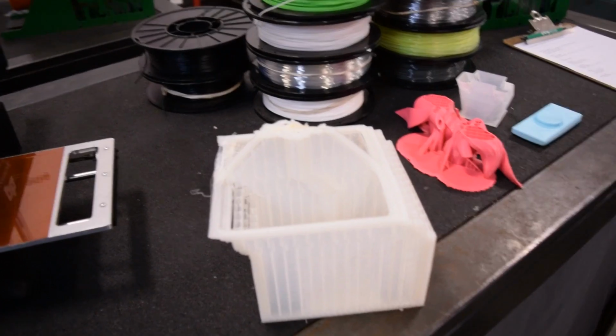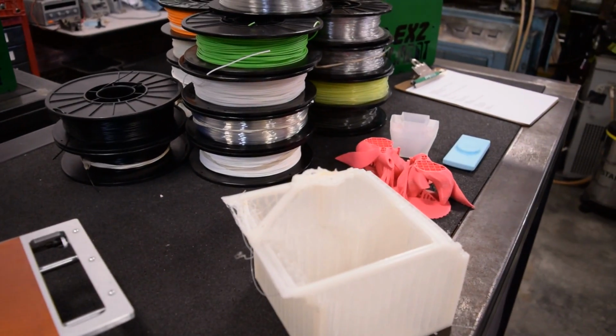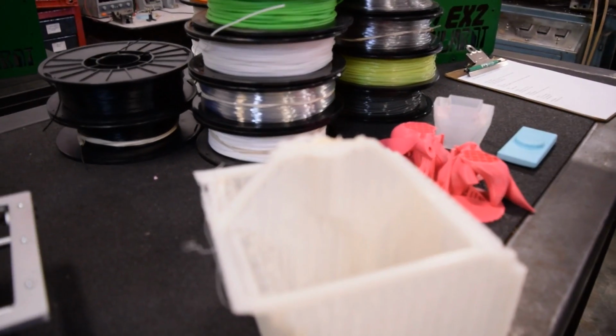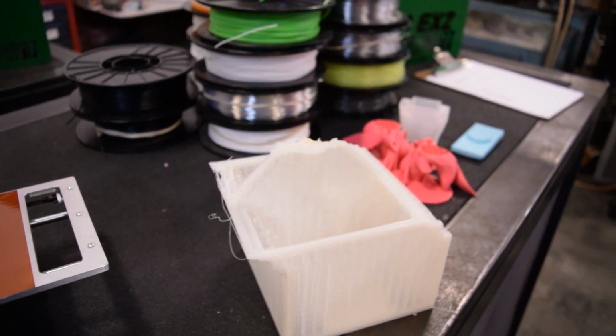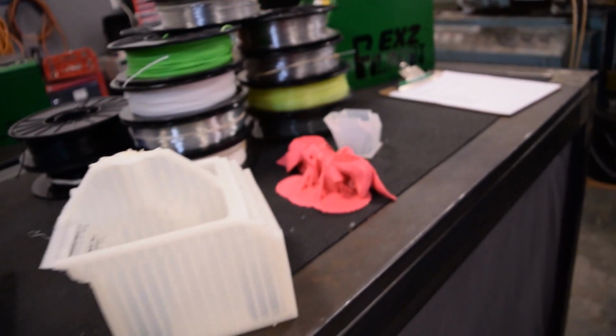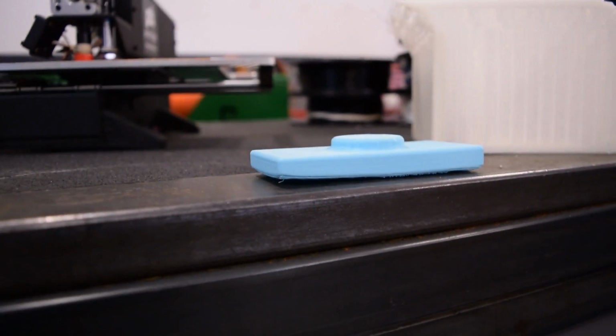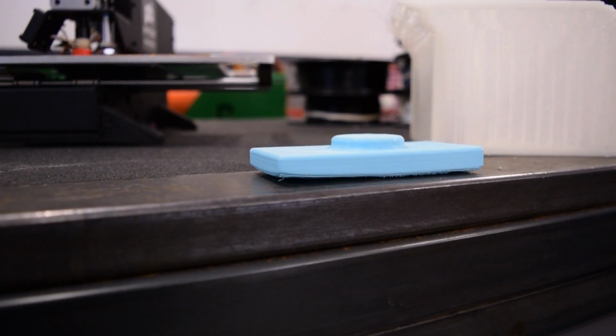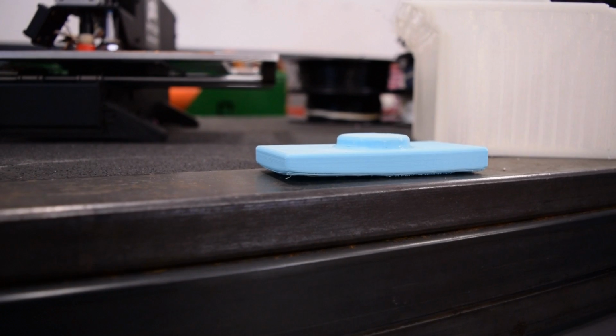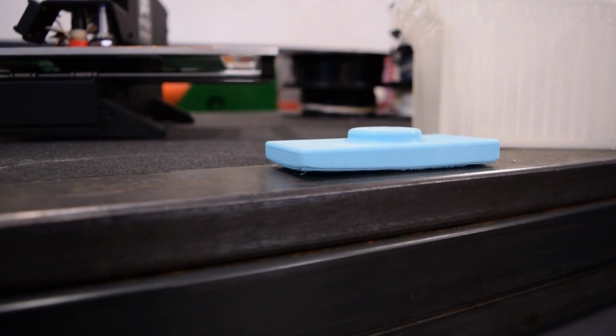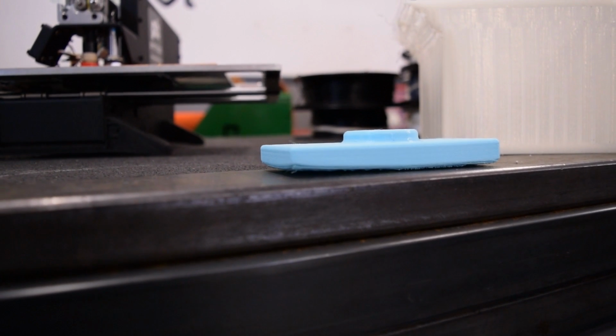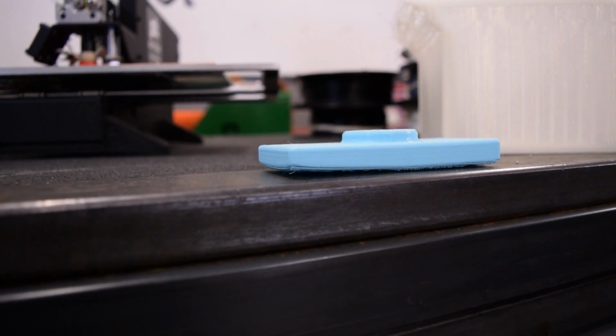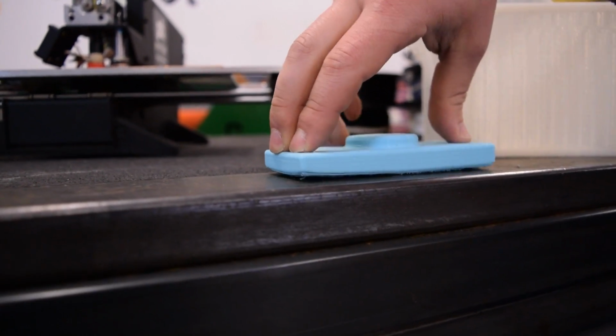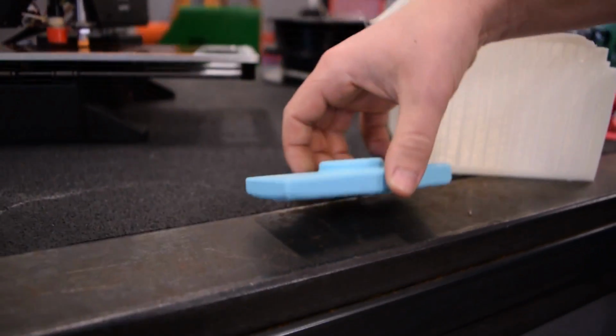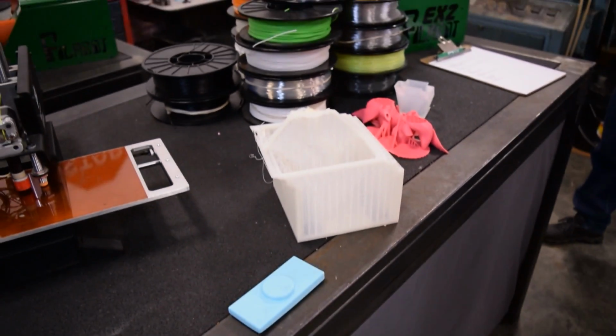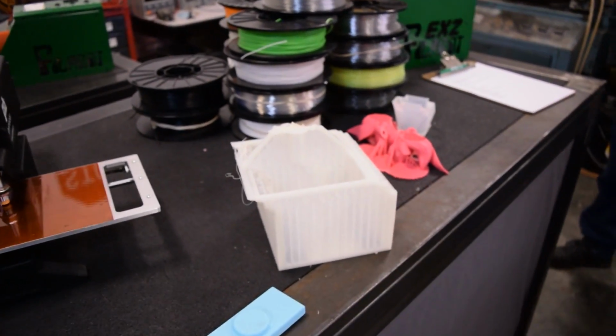This was an example that eventually did that, but a couple of causes are your nozzle catches on the edge from warping, or it warps off the bed. So here's an example of a print that warped off the bed, and this is because polymers have a pretty high thermal expansion, and so when they cool, because they're hot when they get extruded out of the nozzle, they shrink a lot. And if you don't have a good adhesion to your bed, and sometimes you can't prevent it because polymers have a really high shrinkage that can't be prevented, you'll get it peeling up from the bed, and it will just fall off.